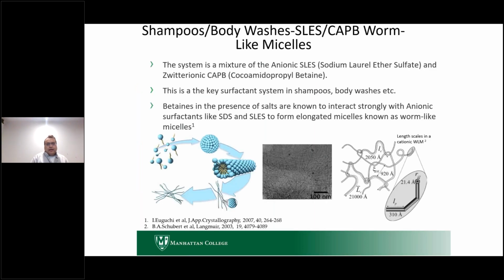it's going to have an impact, right? As I said before, if you look at just one aspect, like building up viscosity and structure in a shampoo or a body wash, the system is this very simple anionic sodium lauryl ether sulfate and the zwitterionic cocoamidopropyl betaine. And the betaines in the presence of salts are known to strongly interact with these anionic surfactants to form elongated worm-like micelles. At that low pH, although it's zwitterionic, the betaine takes on a slightly cationic nature. That cationic-anionic interaction, and then in the presence of salt allowing more screening of the charges, allows you to build up these long worm-like micelles.